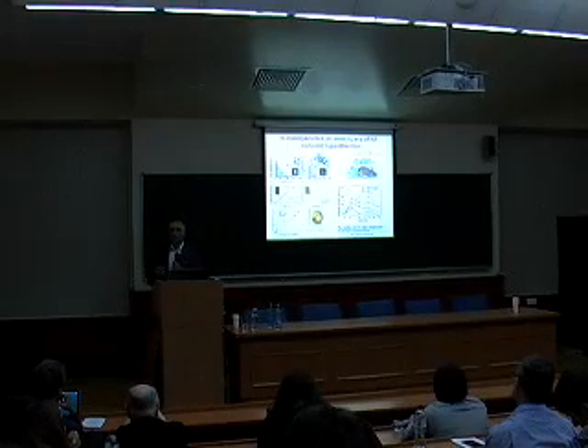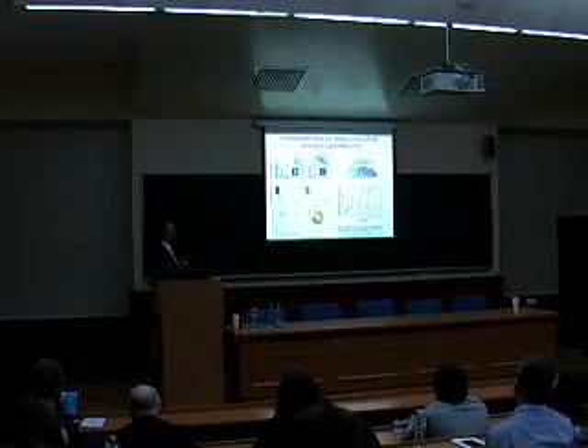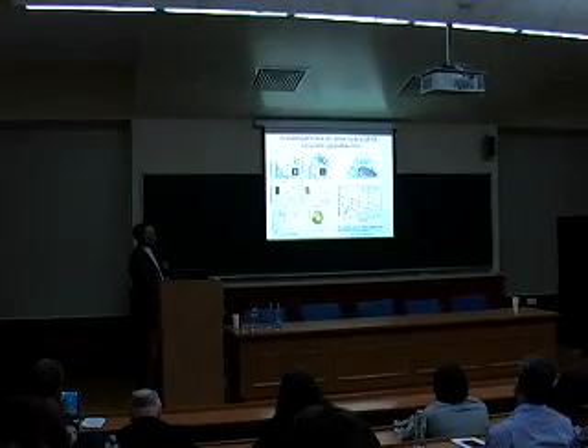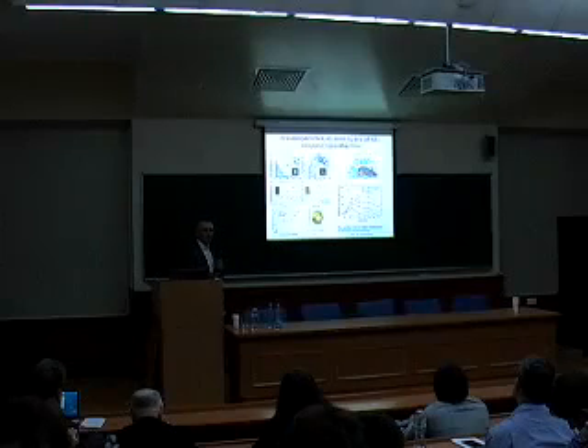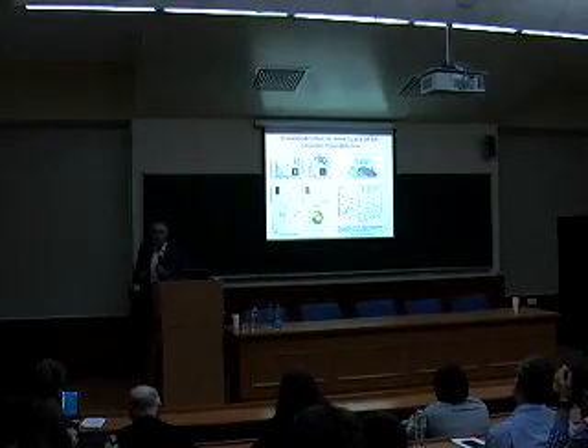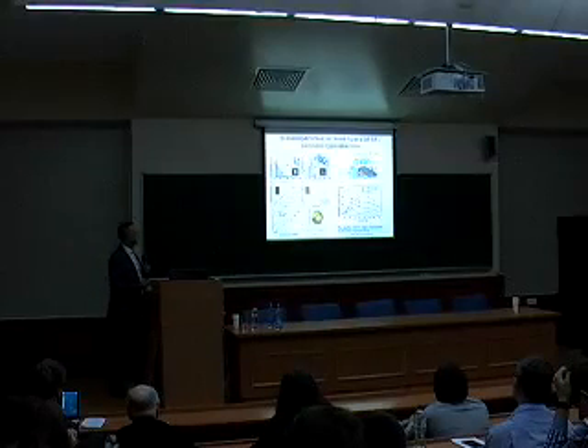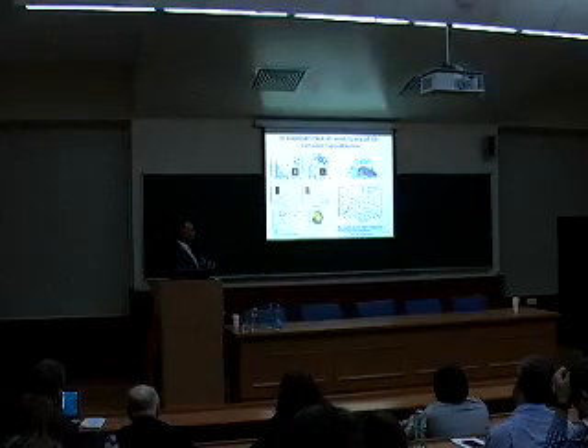But in this case, in case of silicon nanoparticles, we do not have magnetic losses. We have another origin, which was discovered in our experiments. This origin is local electrical current, because the electric field in radio frequency radiation initiates motion of ions, mainly intrinsic ions of water. And nanoparticles are sensitizers, a hot spot of such current. And we observed a strong increase of temperature of suspension with nanoparticles.